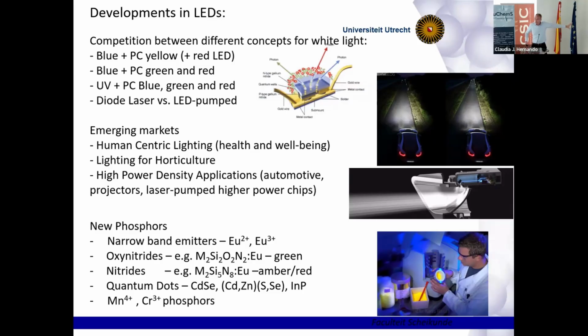And in the field where I work, there are many new materials being discovered. Narrow band emitters are also good for energy efficiency. Oxynitrides, nitrides, quantum dots. And I explained that the optical properties of lanthanides are really unique. And this morning it was mentioned that initially the EU said, well, we have to go for replacement of lanthanides with other ions, substitutes. And indeed, the efficiency of lanthanides is unparalleled. And for many applications, we cannot replace them. But in some applications, 3D transition metal phosphors are also doing a good job. For example, manganese 4+.